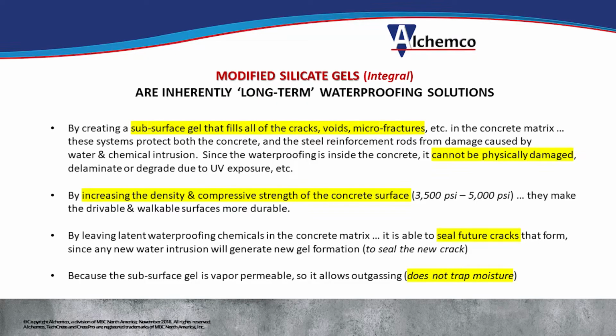The test that we have done shows it's going to increase from 6, which is the regular 6 on the Mohs scale, which is regular for concrete, to a hardness of 8, which is the equivalent of granite. So you're going to have a stronger concrete. And also this material is going to be able to seal the future cracks, not only the existing cracks in the concrete, and I'm going to show that later on, but also the cracks that happen after the application.